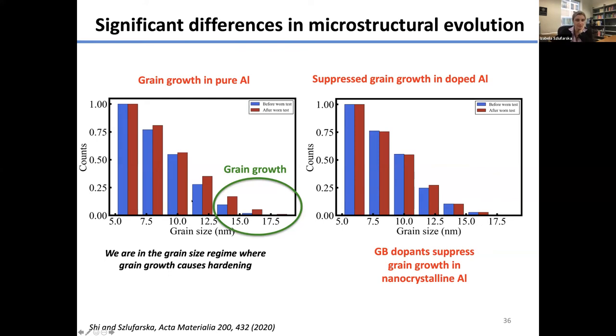This is a side point, about why nanocrystalline aluminum got better after the grain growth. This is very specific to these small grain sizes. It turns out that 10 nanometer grain size is in the regime of the so-called inverse Hall-Petch regime. And this regime is unique in that grain growth here leads to strengthening of the material, and eventually it turns over. But this is a side point. The main point of the story here is that the dopants can suppress and stabilize the grain size. So if you synthesize nanocrystalline or ultrafine grain aluminum, the dopants are going to stabilize the grain size.